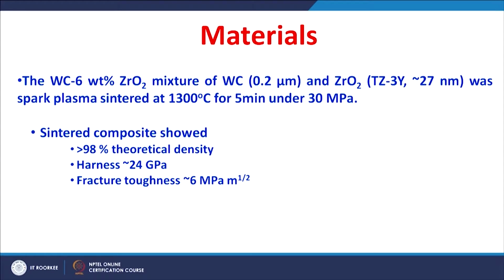These two powders, tungsten carbide and zirconia, were mixed to make a tungsten carbide 6% zirconia powder mixture. This mixture was spark plasma sintered at 1300 Celsius for 5 minutes under 30 MPa pressure, with a high heating rate of around 600 Kelvin per minute. All these ceramic composites showed a very high density of more than 98% of the theoretical density, a hardness of around 24 gigapascal and a fracture toughness of around 6 MPa root meter.